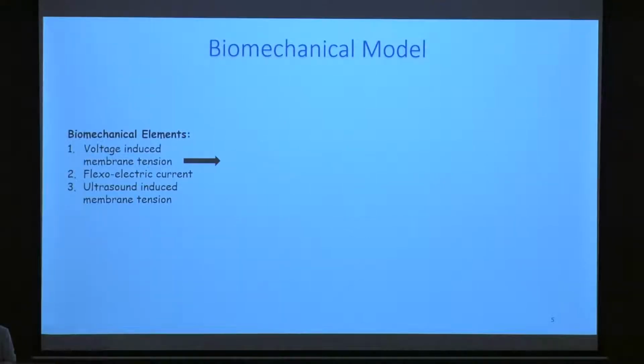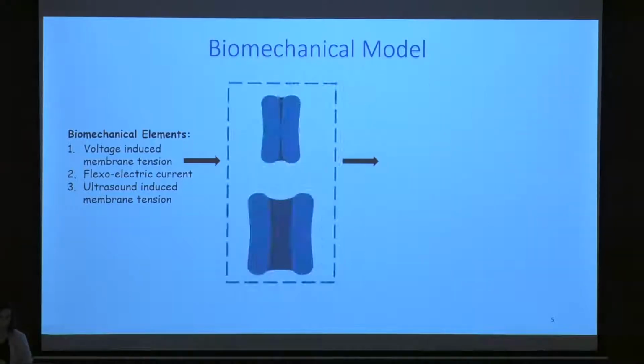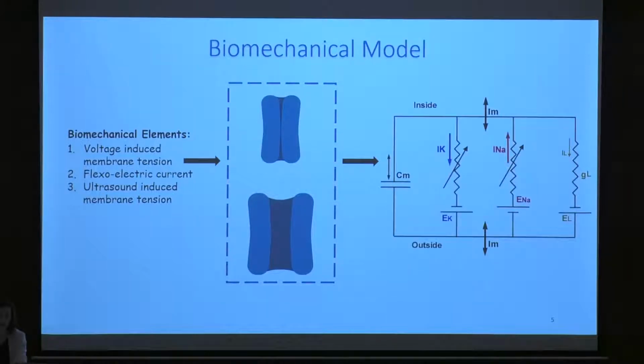So our biomechanical model considers 3 main components. The 3 components are the voltage-induced membrane tension. There's voltage in the membrane, and it changes during an action potential, which causes tension to vary in the membrane. The flexoelectric effect, which is basically due to the nature and the curvature of the membrane. There are oscillations that occur and cause currents to be produced. And there's the ultrasound-induced membrane tension, which we will discuss thoroughly later. These mechanical effects actually affect ion channels. They cause the ion channels to open and close or affect their normal behavior. And this is how the mechanical model will be coupled into the electrical Hodgkin and Huxley model.